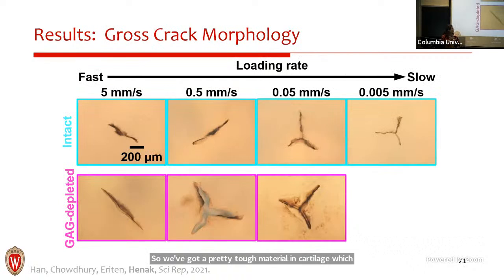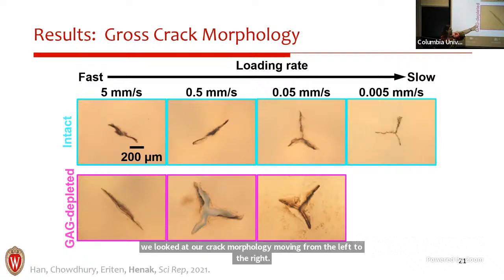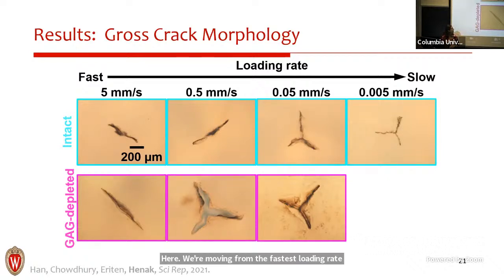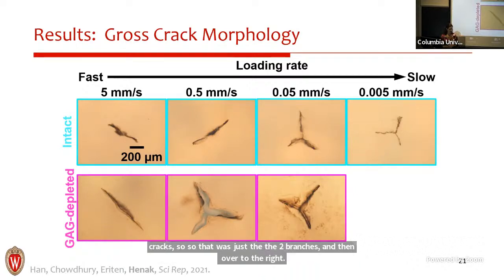When we looked at our crack morphology, moving from the left to the right here, we're moving from the fastest loading rate, so pre-relaxed, over to the slowest loading rate. In the fastest loading rate case, we consistently saw these 2-branch or line-shaped cracks. So that was just the 2 branches. And then over to the right, we consistently saw the star-shaped or the 3-branch cracks.